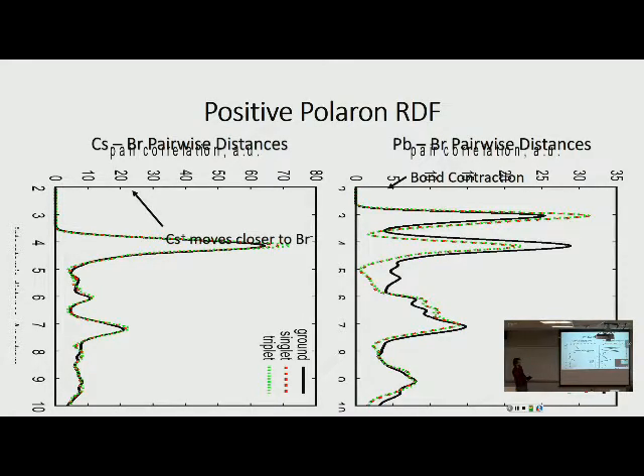You can see for the closest bonds you get bond contraction, or the bonds become shorter, because there's more of them within this region. So it indicates some bond contractions here, and same with the lead bromide pairwise distances. The offset of dashed lines compared to the solid line decreases with distance. For smaller interatomic distances, the green and red substantially differ from black, and as we go outwards, it decreases. Right, so that's just the effect that you guys are looking for.